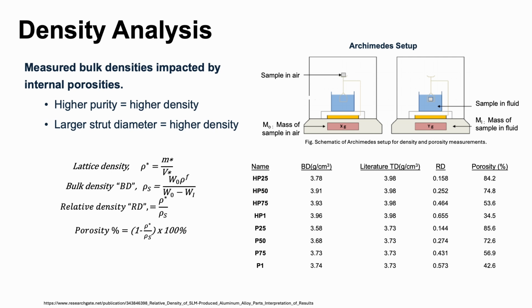The density measurements were calculated using a variety of methods. The bulk density of alumina was measured using the Archimedes principle, where we measured the mass of the sample out of water and then in water. Since there's porosity, the bulk density differed slightly. The reported theoretical density was found in literature, and the lattice density was measured by taking the mass and dividing it by the measured volume. The relative density was then found by dividing the lattice density by the bulk density, and the porosity was measured by subtracting the relative density from 1.